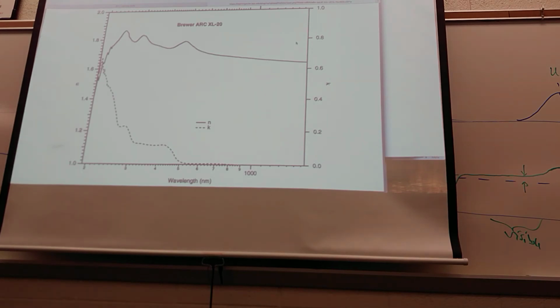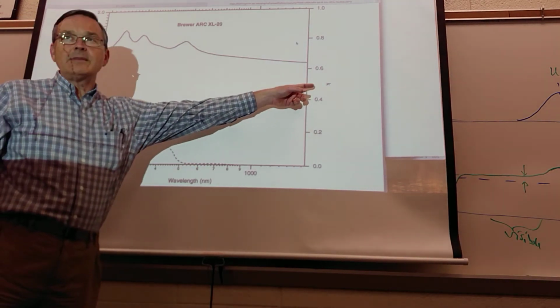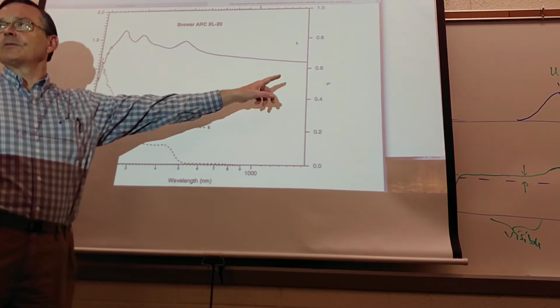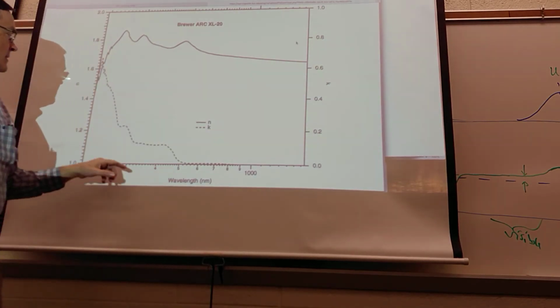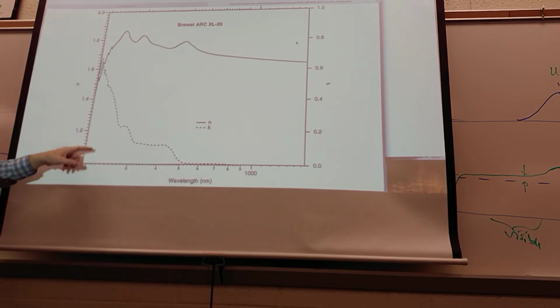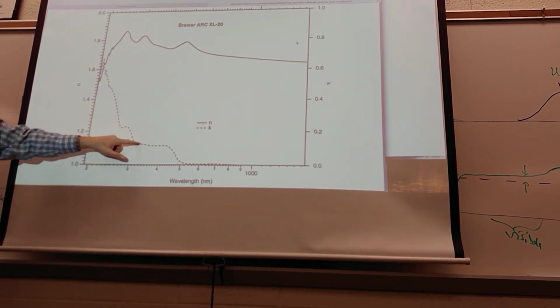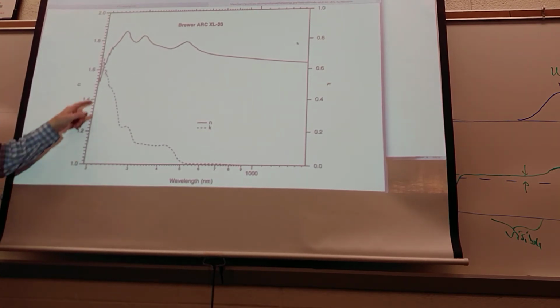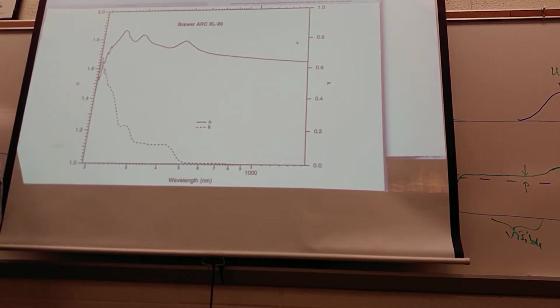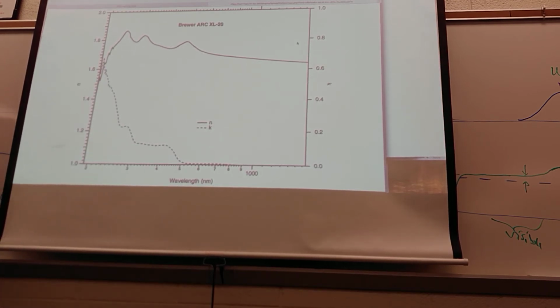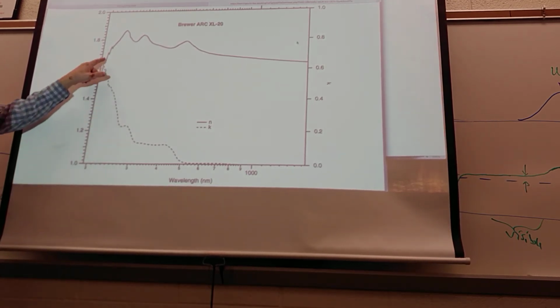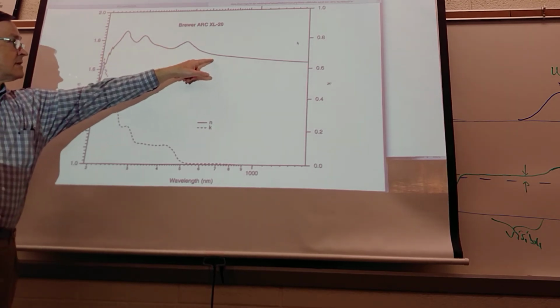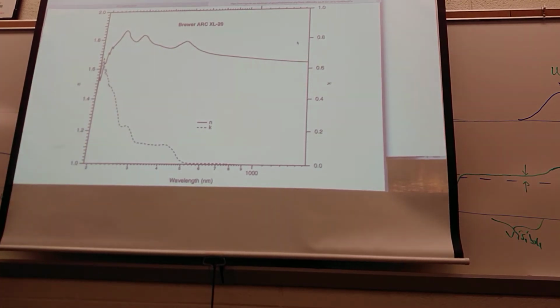Okay, so over here, K, that's the imaginary part of the refractive index, which is absorption. And this is wavelength. And so here is our measured absorption spectrum. So it's not just a peak, it's something more complicated. But it doesn't matter, you can still do this. It's just a numerical integration. And this is the refractive index that we calculate because of that peak, or rather that absorption.